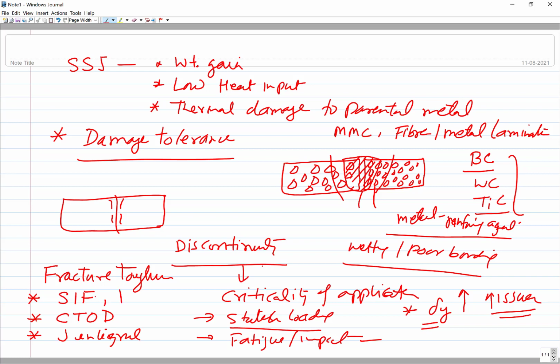The stress intensity factor is the most common one used for design purposes. It is represented by the letter K. Since things are mostly designed based on tensile stress conditions, for the tensile mode of fracture, we show it as K1. When it is shown as K2, it means the stress intensity factor for mode 2, which is for shear loading. I'll talk a little later about what these different modes are. Similarly there is a mode 3, which is also shear but in a different way. Mode 1 is for tensile stress conditions, called the crack opening mode.